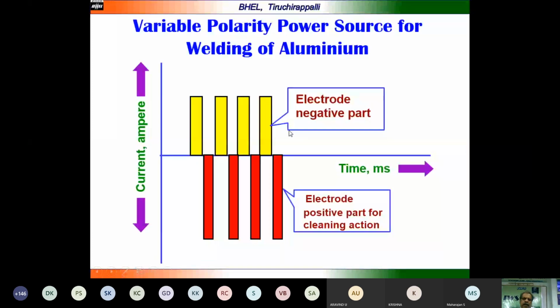As we saw earlier, you use alternating current, AC, for welding of aluminum. 50% of the time, when the electrode is positive, the self-cleaning action is taking place, and 50% of the time, when the electrode is negative, the welding is actually happening. So instead of having 50% of the time for cleaning, the cleaning time can be minimized so that the deposition time can be increased to improve the quality of the process. Variable polarity power sources have been developed.